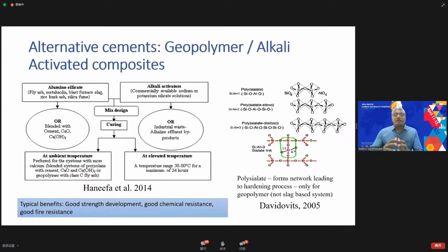The other route is to look at an alternative chemistry rather than Portland cement for the reactivity of abundantly available aluminosilicate materials. We start utilizing alkalis to activate these materials, so alkali-activated composites, or geopolymers as we sometimes call them, can be a quite useful option.